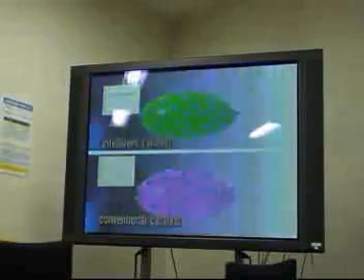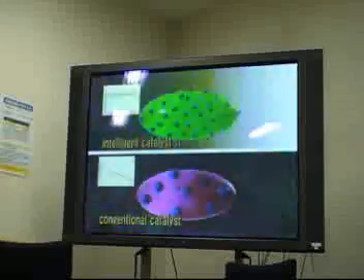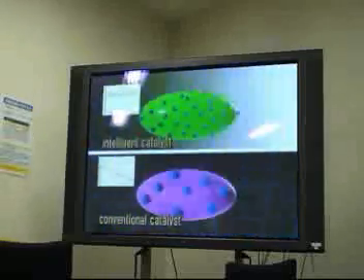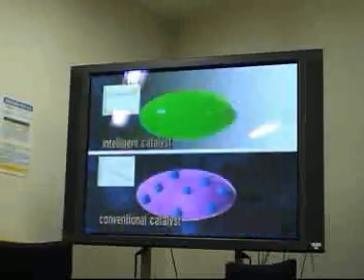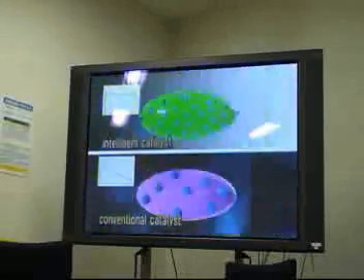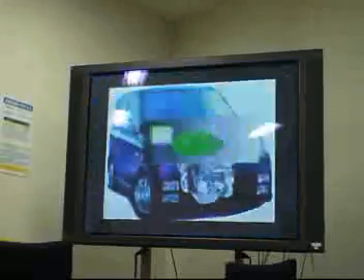It was found that the metallic atoms of the catalyst moved into and out of the crystal grains during the redox cycle. This movement prevents the metal from coagulating and growing larger. Thus, the intelligent catalyst is able to maintain its initial condition indefinitely. This catalyst is already being used commercially, which is helping to save precious metal resources.